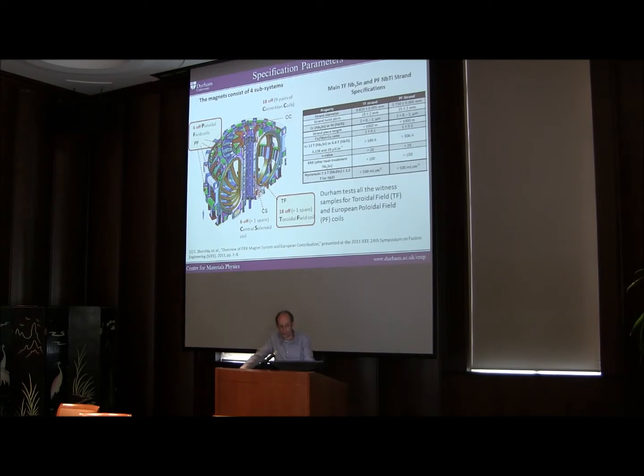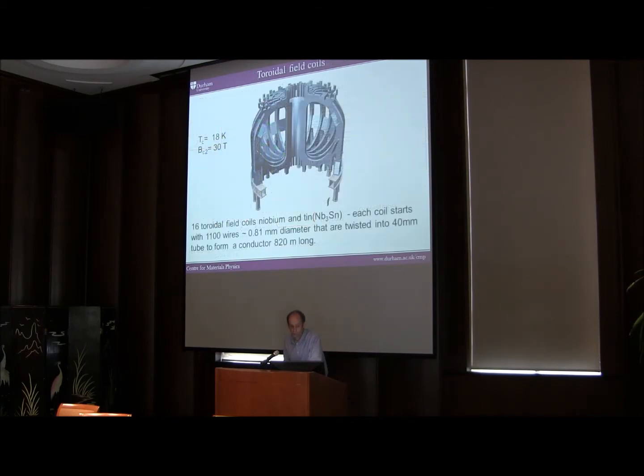At the moment, the toroidal field coils, which are the ones in gold there, I keep pointing at the screen here, which you can't see, of course. Durham is contracted to ITER to measure, validate and confirm the condition of all of those coils for ITER, so all the toroidal coils. And for the poloidal coils, which are the ones that go around the outside of the reactor here, some of those are made in Europe, some of those are made elsewhere. The ones that are made in Europe, again, Durham has the contract to do the testing of those and the confirmation that they are fit for purpose.